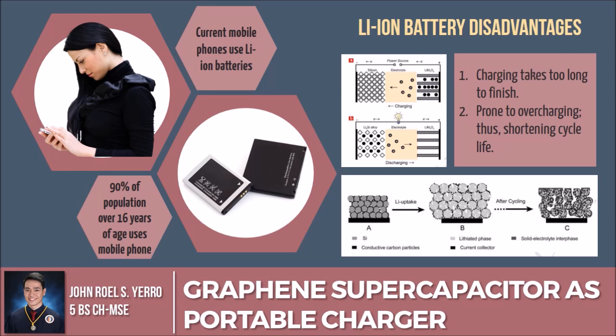During lithiation, silicon anodes expand enormously up to 400% of their original size, then reduce to a varying size during dilithiation. This expansion produces stress and strain on the silicon particles, causing cracks and breakage. This yields low capacity stability and rapid capacity degradation over a number of cycles, or in other words, shortening battery life.